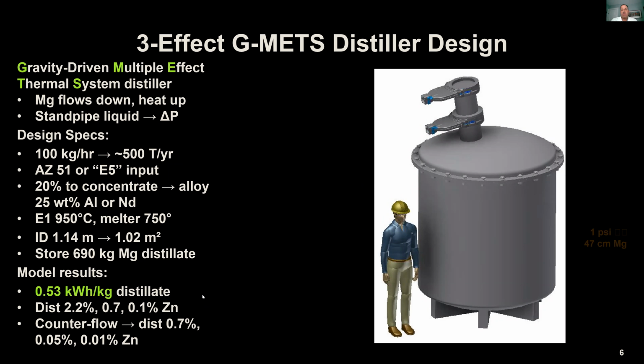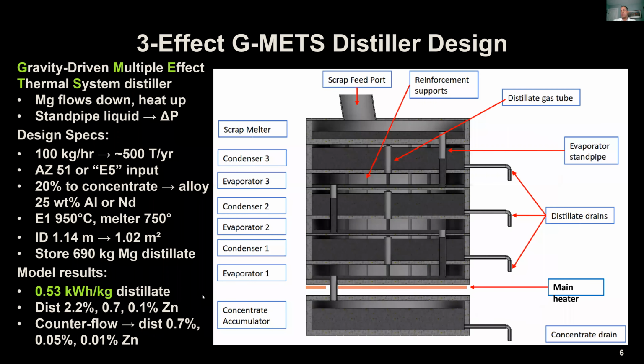This is the rough scale of a 100 kilogram per hour pilot magnesium distiller. And here's what the inside looks like. It is a multiple effect distiller in which a single heater distills material in multiple evaporators and condensers called effects at decreasing pressures, effectively multiplying that heat's effect. Liquid magnesium flows from top to bottom. Liquid magnesium is the dark gray in here, with some of it evaporating off in each effect and the remainder flowing down to the next evaporator.